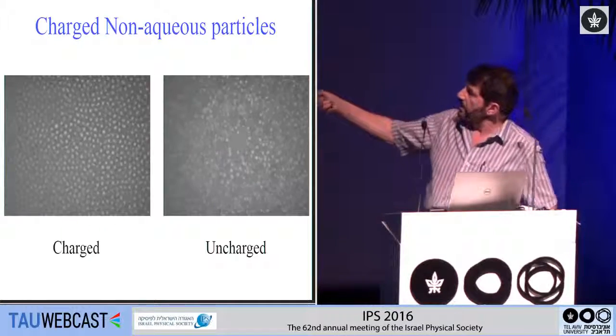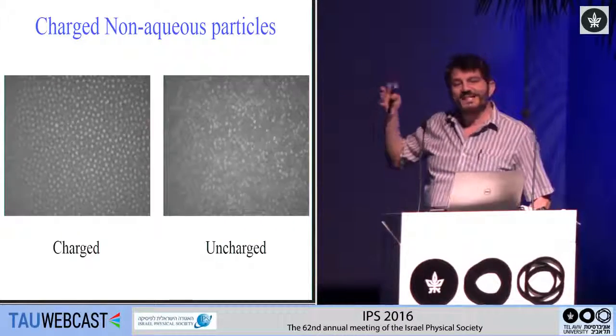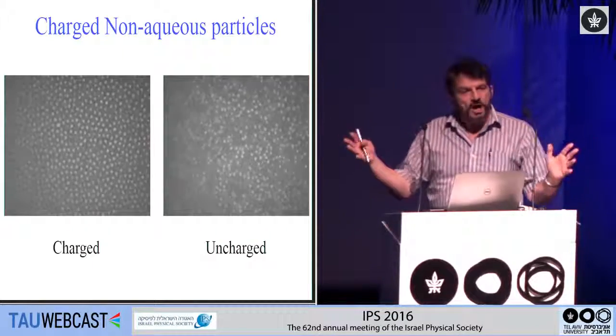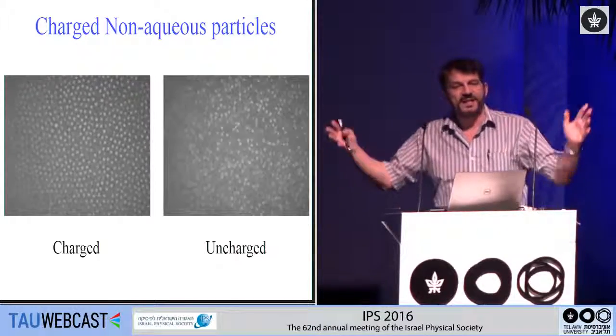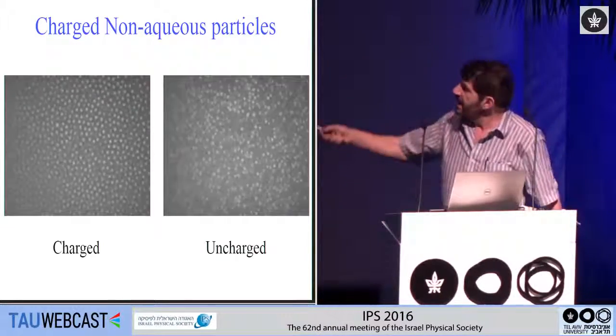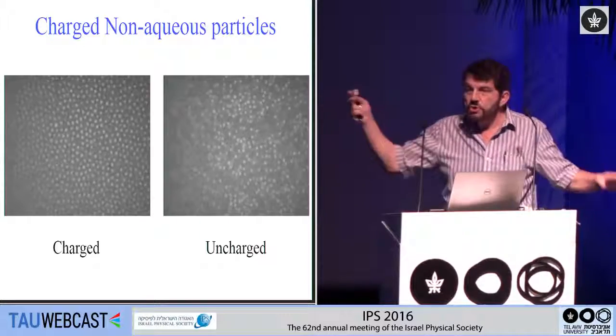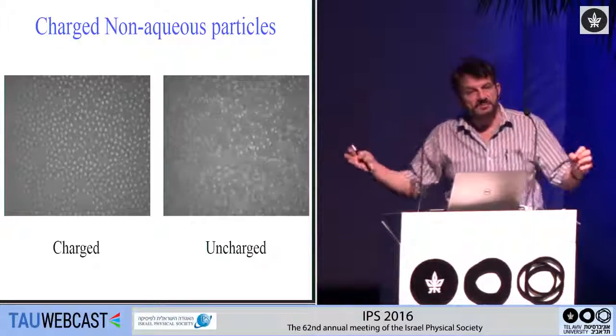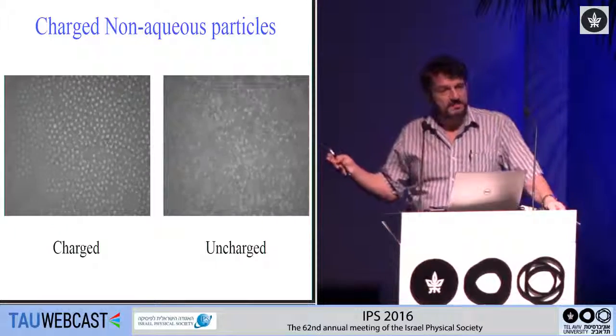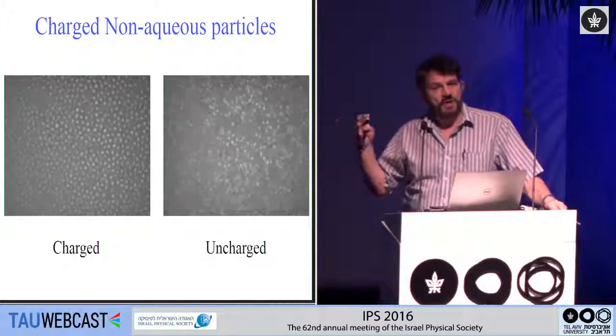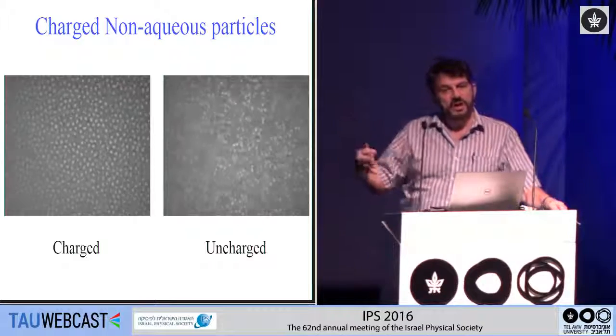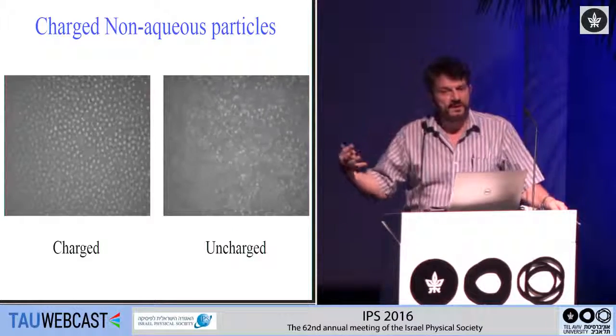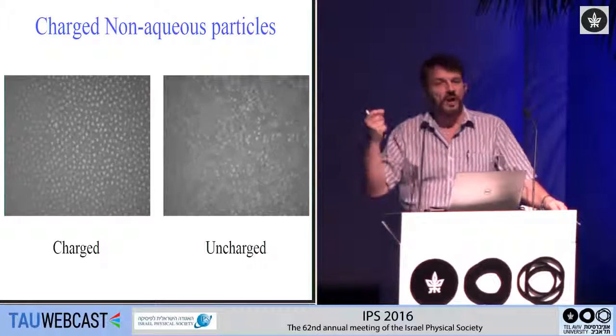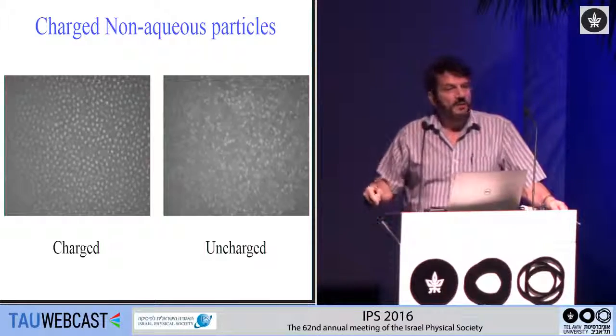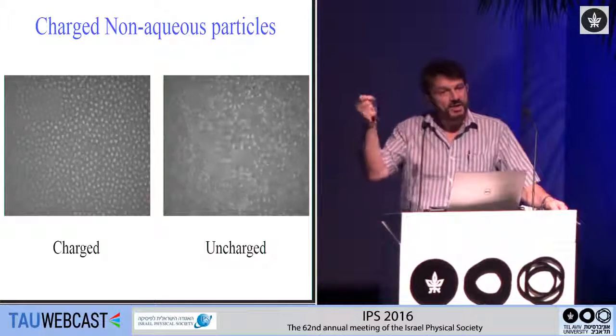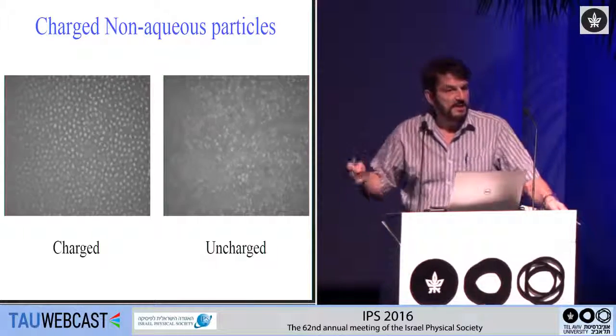Now you can see that the particles really have a characteristic spacing between them. They're charged. They feel the repulsion of each of the particles, so they can never approach one another very closely. And instead, there's a certain ordering that you can see due to the fact that they're charged. Now, in this system we can adjust both the charge and the concentration. We can adjust the charge essentially by changing the amount of surfactant in the solution, changing the amount of charge that can be solubilized in the oil. And we can adjust the concentration just by changing the number of particles in the suspension.